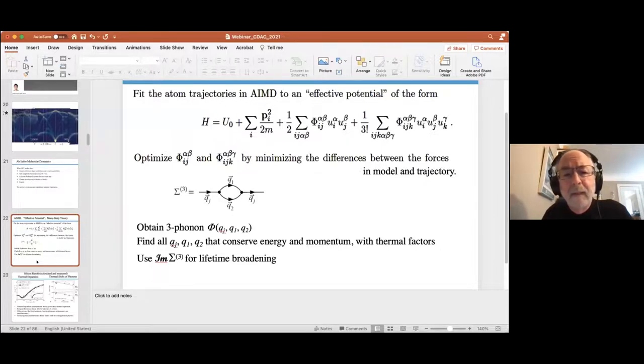Not our experimental data, but there's a bunch of points here, and our ab initio calculations maybe are a little better, but it's not a big improvement. So this is very annoying that it was working. The quasi-harmonic theory, which is much simpler than handling all of the atom vibrations about their center sites, was working with the wrong phonon physics, because that's all you've got. You've got the phonons for the entropy, and you have the elastic expansion, which is working against that.